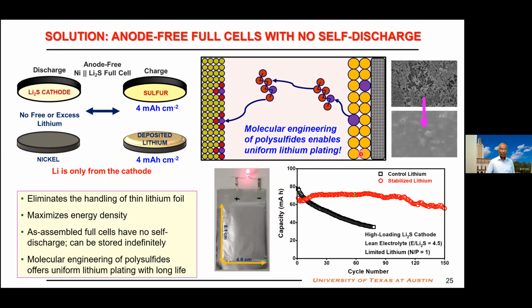So to understand what is really going on, we have adopted what is called an anode-free full cell. That means, for example, here you take a Li2S cathode, like in the lithium-ion battery. On the anode side, you don't take anything, just the current collector, because you have lithium here. Assemble it like the lithium-ion battery. Of course, in a lithium-ion battery, you will have graphite here. Here, there is nothing there excepting the current collector. So this will eliminate all the hurdles.